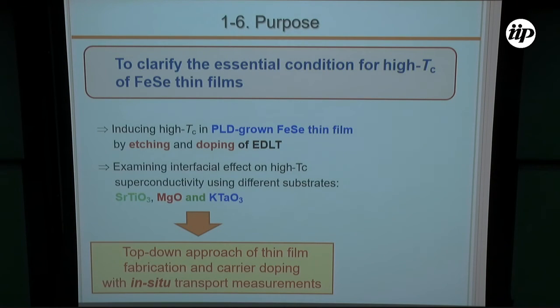Oh, sorry. So in order to clarify the essential condition of high temperature superconductors, we tried to induce the superconductivity by etching and doping. Then we examined the interfacial effect using different substrates.